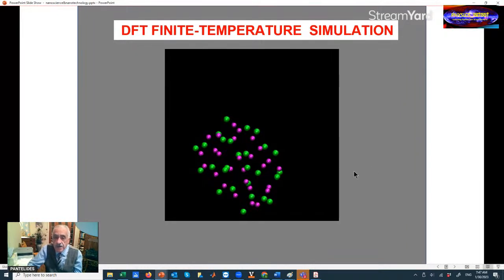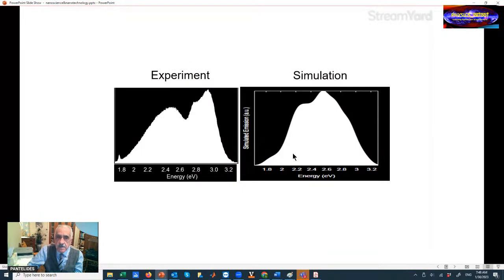And we were able to actually calculate what light such fluxional nanoparticles would emit, and they would emit the whole range of energies. And you know, when you emit the whole range of photons, if you superpose all the colors of the rainbow, you get white. And we calculated the spectrum of what you would measure. The different colors are inside here, and they are superposed on your eyes very quickly. And therefore you see white, and the experimental spectrum was like that. So we explained everything to the great detail.